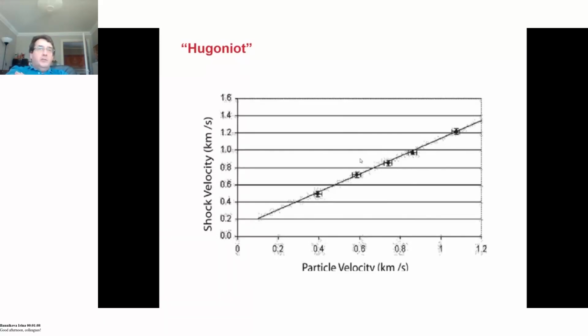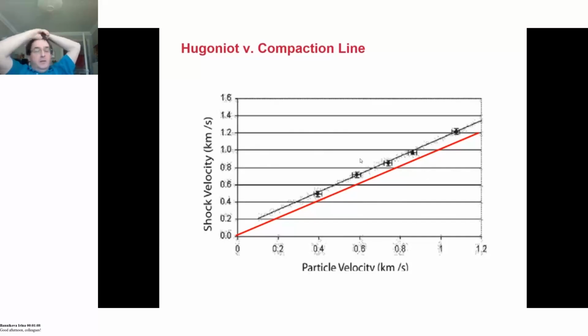So I'm not measuring a shock, I'm measuring a compaction wave. So this response here is basically just compaction, even though the particle velocities are very high. That just shows a simple line of what I'm doing, the shock velocity versus particle velocity, 1-to-1.